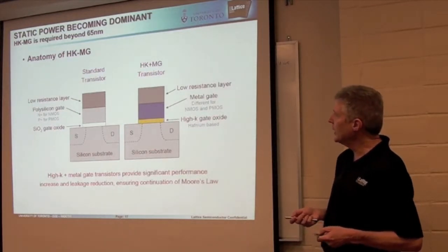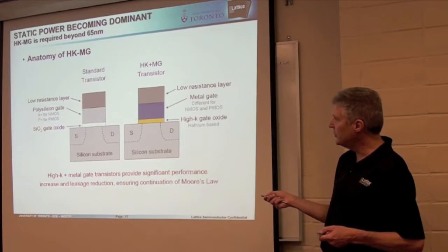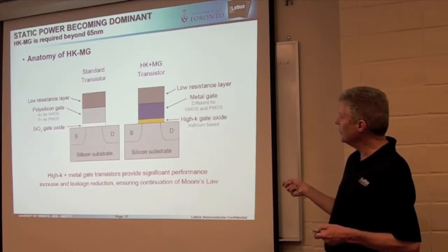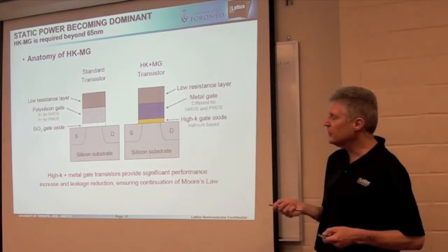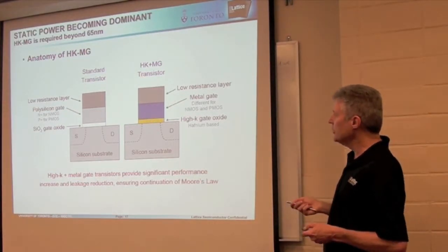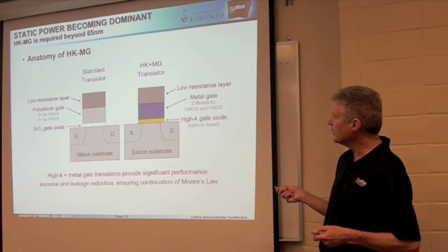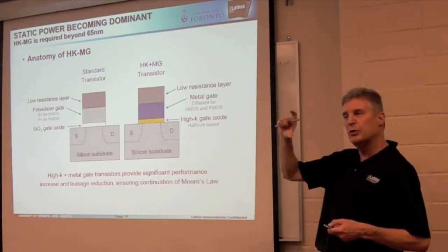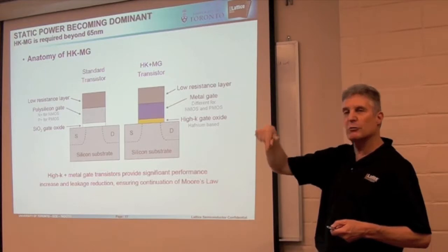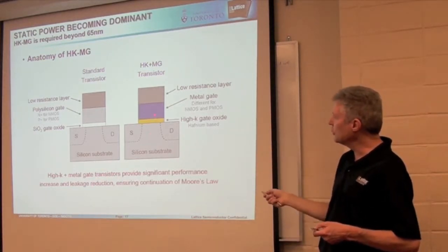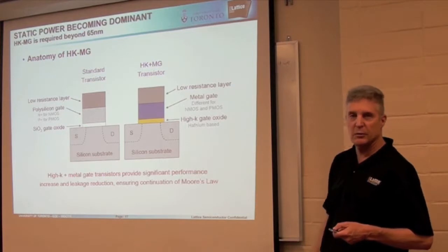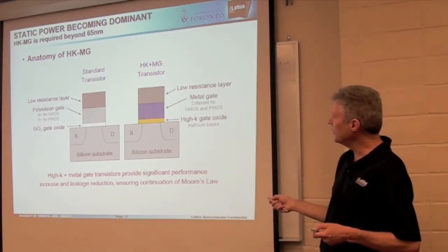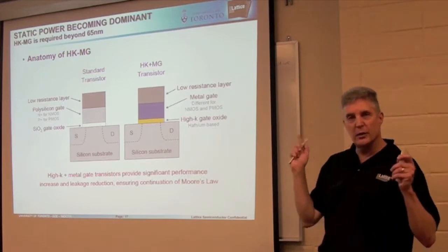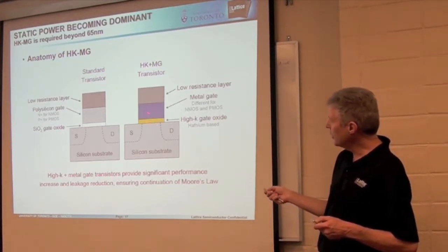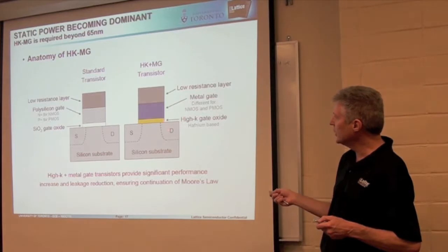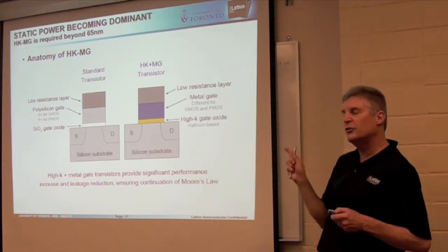So enter the HighK metal gate transistor. It replaces the silicon gate oxide with a hafnium-based gate oxide. It's a different material, and essentially it has a higher dielectric constant. So what you can do is you can make that material thicker, and it will be electrically insulating, but it has the same electrical effectiveness as a thinner dielectric of silicon dioxide. So you get the benefit of the high dielectric constant, which is why they call it HighK. It couples more directly to the substrate and gives you better electrical control while still being able to be a